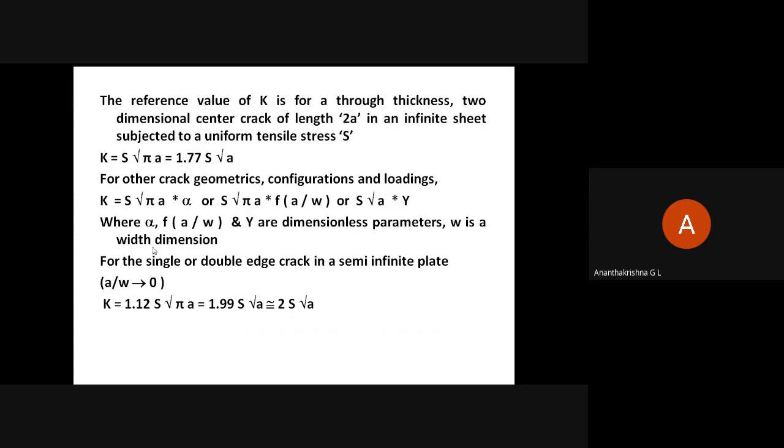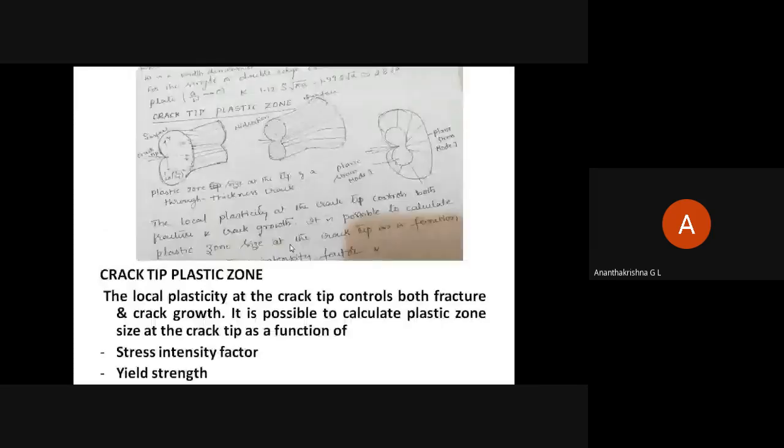And then we arrived at another equation. So finally, we can say K is equal to 1.99 S root A, which is approximately 2S root A for single or double edge crack in a semi-infinite plate. Semi-infinite plate, you can take it as a finite plate of larger dimension. Okay, so that is stress intensity factor.